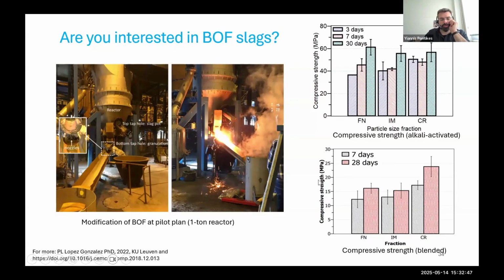I would assume, and I put in 2 more slides here, that some of you have an interest in BOF slags, because ultimately the idea is not that different, and we think of that as a triangle. BOF slags, also being iron rich, can be reprocessed at high temperature in a similar way. These are from examples we've done in Sweden, where we modify the slags. Here you see the performance for alkali-activated materials: in 30 days, close to 60 or 55 megapascal. The performance is lower if you do blended cements. So no alkalis here, but you can still reach 20-plus megapascal in 28 days. So this is still decent for many, many applications.